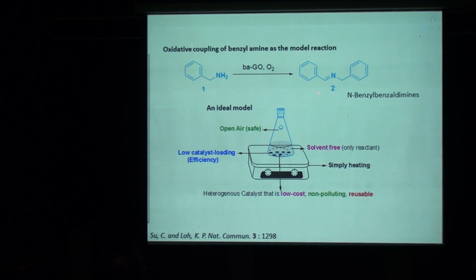We use this chemical reaction. Excuse me if it's boring, if you're not familiar, but basically this chemical reaction is a classic reaction just to show how we can couple this. We call this a benzylamine. We use BAGO as a catalyst. This molecule couples and it forms this. We call it N-benzylbenzaldimine. In this kind of chemical reaction, it's an ideal model. We don't need any solvent, solvent-free. We only need to use BAGO and the reactant. Solvent-free, only reactant. Open air, safe. We do not need to use high pressurized oxygen, just air. Low catalyst loading, just a little bit, just about 5% weight loading of BAGO.